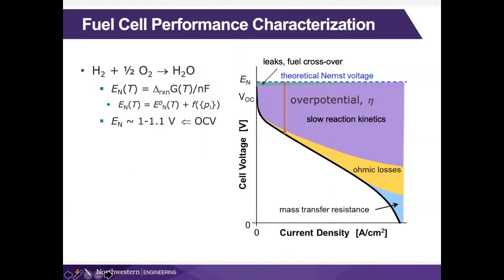The way that we characterize fuel cell performance is to look at the voltage as a function of the current density. So how much current are we passing through that membrane that I showed you, basically that electrolyte layer. We are normalizing it per area because that's a way to be able to compare different cells to one another. So we start off at the Nernst potential. Ideally, we might have some leaks and crossovers. But as we start to pull current from our cell, we start to lose some voltage.